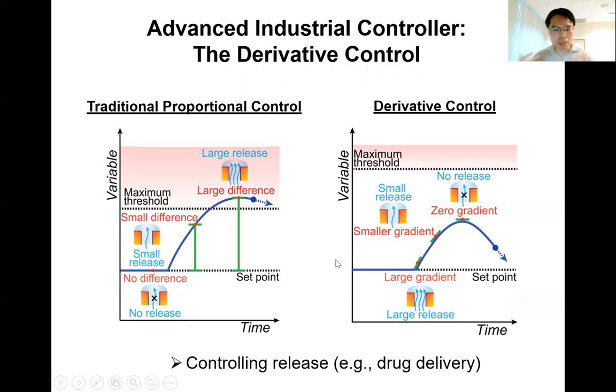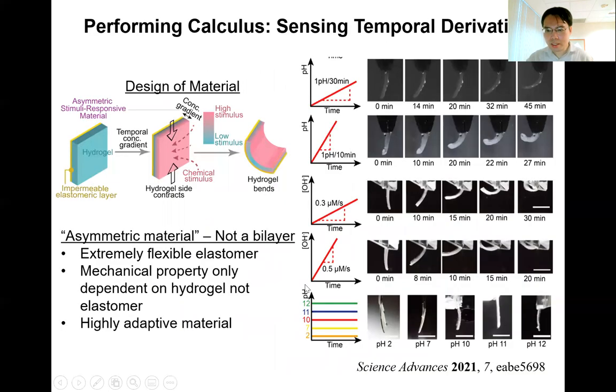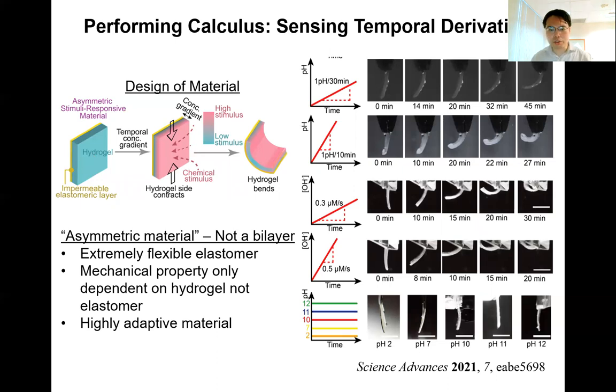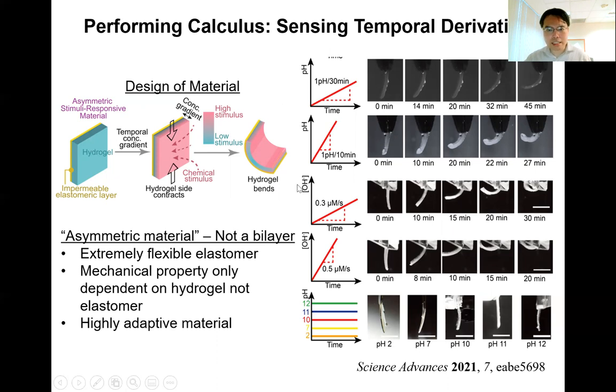This type of operation may be useful for many different applications, including controlling the release for the field of drug delivery. The question is how can we design a simple material that can analyze the derivative of the surrounding environment? Here we have a slab of stimuli-responsive hydrogel and we coat one side of this hydrogel with the impermeable elastomeric layer. Because one side is impermeable, only the other side of this hydrogel receives the signal and contracts. Because only one side contracts, the hydrogel bends in this particular manner, and the rate of bending is the way to sense the derivative. So this material is an asymmetric material — it's not a bilayer.